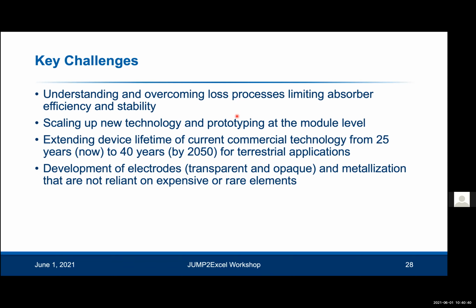And right now in the UK, there's a gap between technology readiness levels from 1 to 3 and beyond that. It's also important to extend device lifetimes from where they are right now, which is about 25 years, to 40 years by 2050. And this is important to reduce the levelized cost of energy. And it's also important to develop materials, especially electrodes, which make up quite a large fraction of the cost, based off non-expensive and non-scarce elements. So going silver-free and going indium-free.